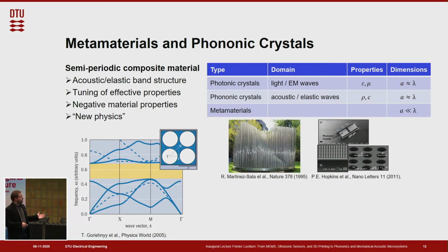Besides this band gap, which in the original phononic crystals is created by what is called Bragg scattering, we also have what is called local resonator effects. So small resonators, microstructured resonators that absorb energy at specific frequencies, which then again lead to a band gap, or a region where the wave cannot propagate through the material.